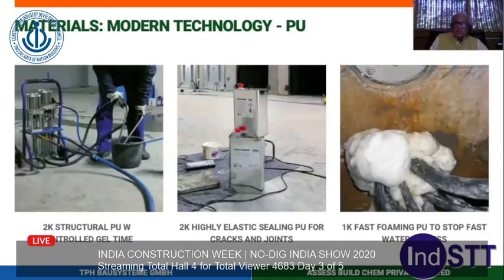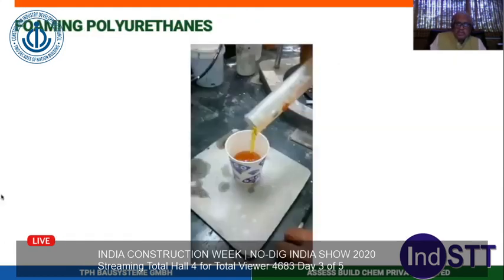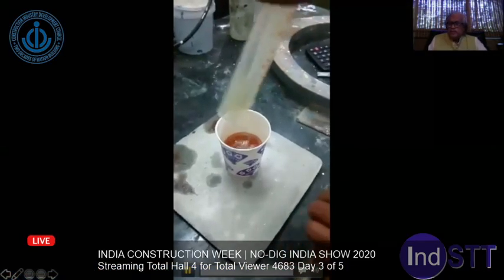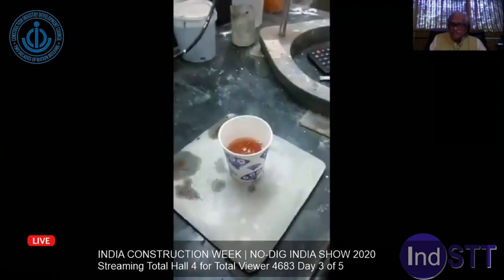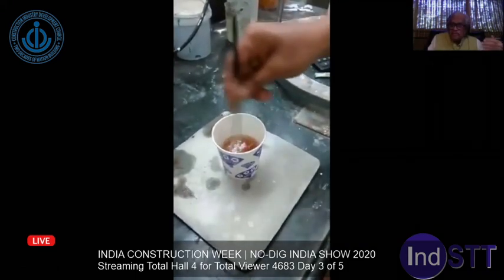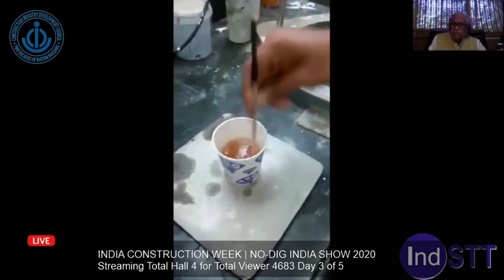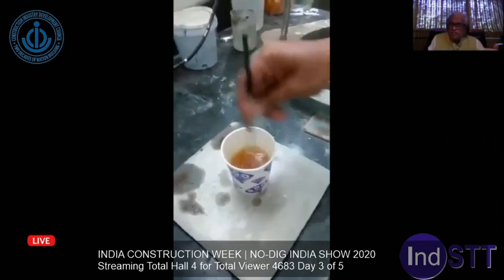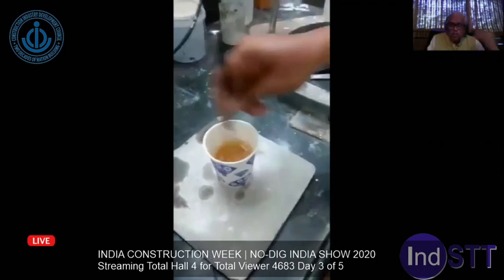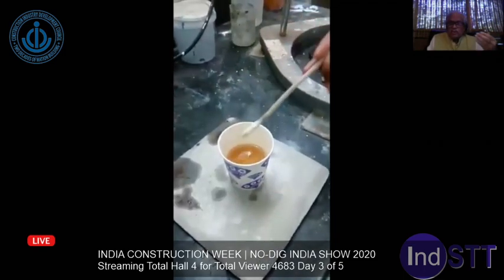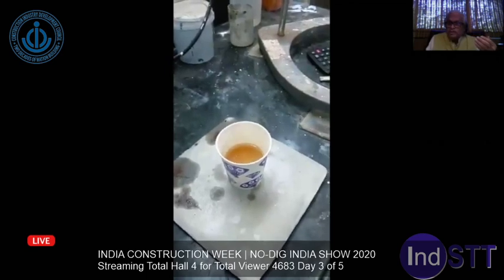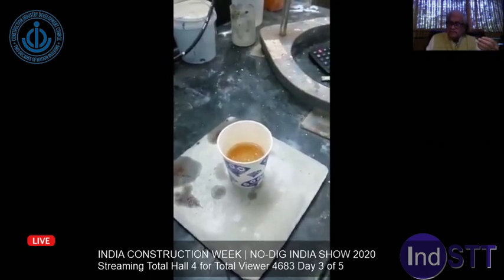So polyurethane is not the foams alone. Foam is the basic thing, like 1-component foams which are used for very low pressure injection. So this is how it forms. The moment the material comes into contact with water, if you put a 1-component foam, it starts foaming. Now this is a very important thing that I'm saying. This can foam from 5% or from 3% up to 75%. So when you are purchasing the foams, it is very important to know what its expandability is.